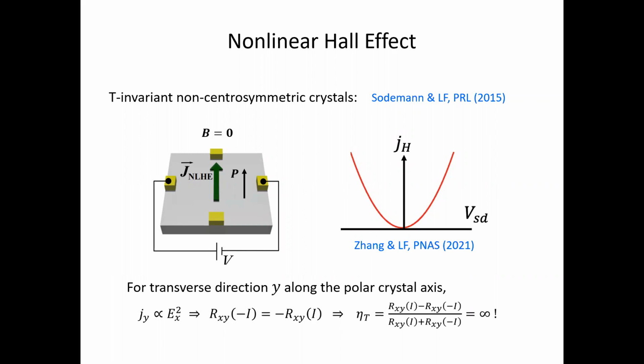We found that actually, even in time reversal invariant, meaning non-magnetic materials, as long as the crystal structure breaks inversion symmetry, for example, if it has a polar axis shown with this P here, we can actually get a transverse current in the presence of applied voltage. So the voltage is applied in the X direction, and a transverse current develops along the polar axis, which is labeled as the Y direction. Again, this is allowed by symmetry. So the linear response is forbidden, but a quadratic dependence is allowed by symmetry. Okay, so this is why we call it a nonlinear Hall effect.